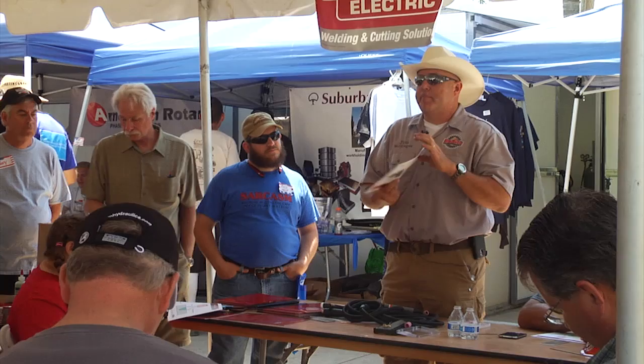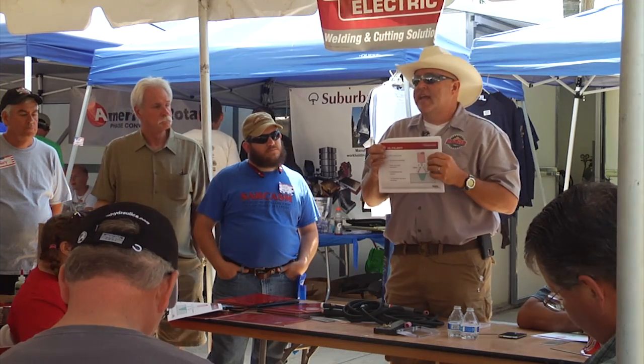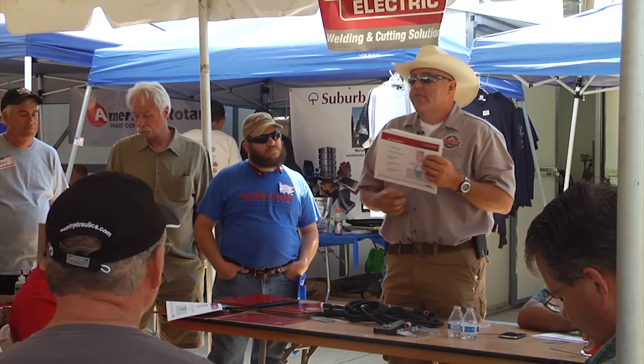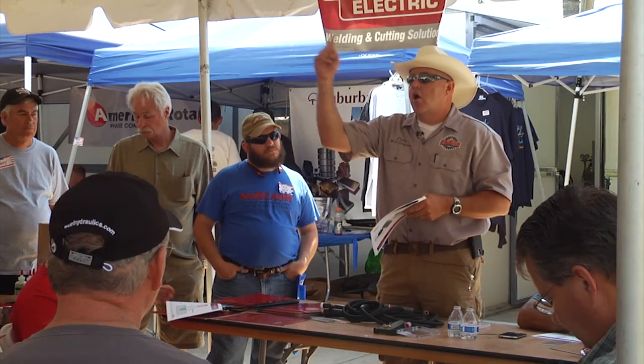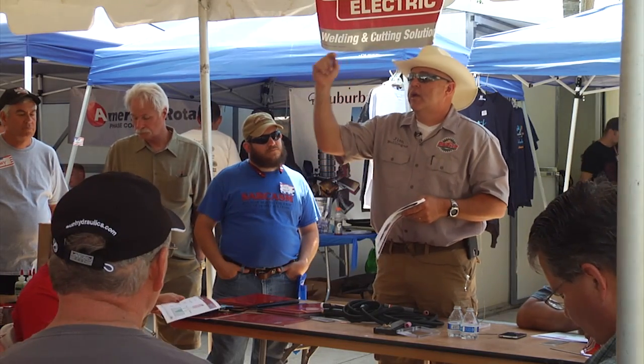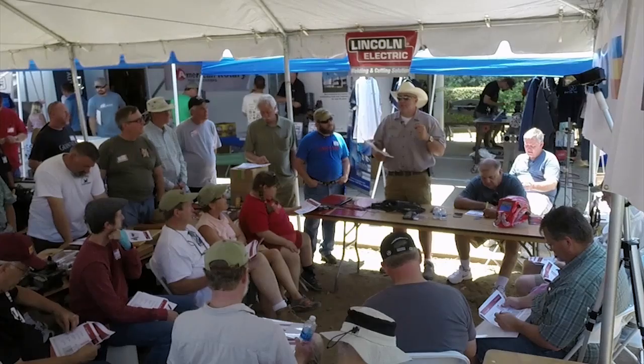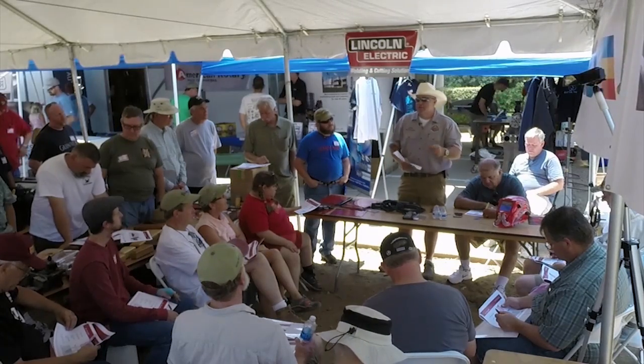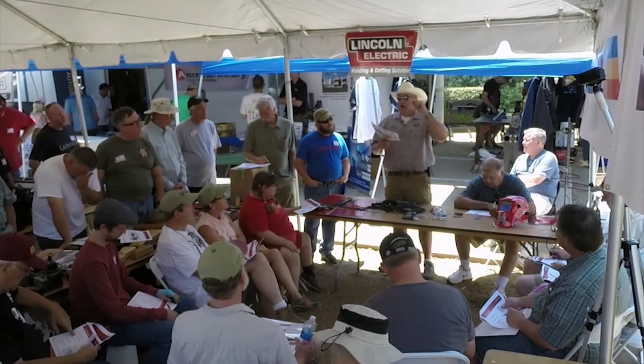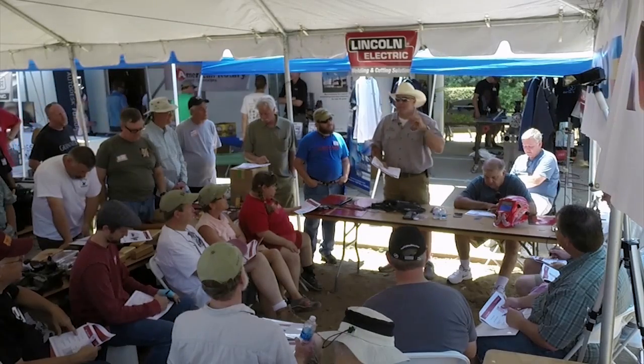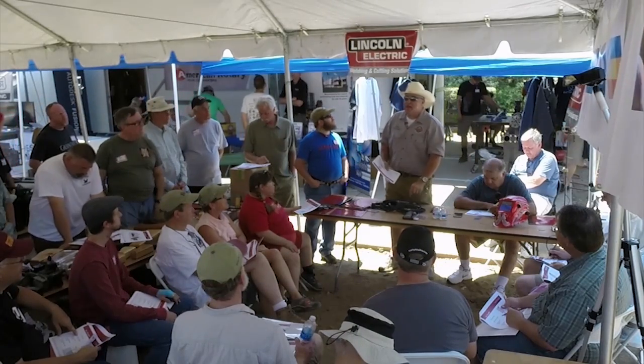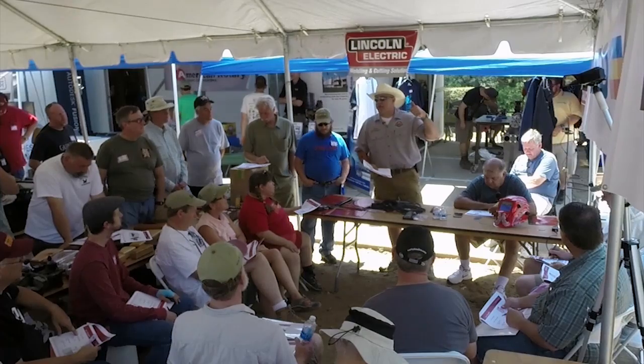In DC polarity, see there's a little negative next to the DC? That's DC electrode negative. It always refers in TIG welding to the electrode. 70% of the heat is in the plate. Do you see that? That means that our arc that we're creating, 70% of the heat is being driven into the plate, 30% is into the electrode.